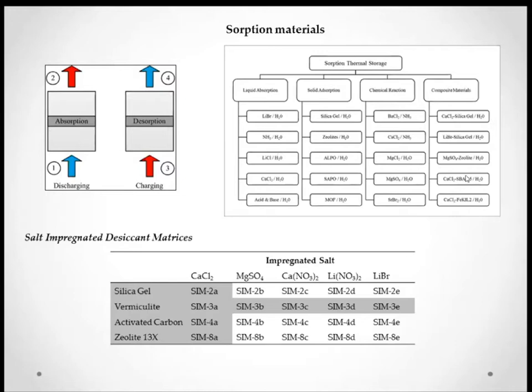Different materials are available in the literature, mainly composite materials using different host matrices to keep the salt inside, with the absorbent salt combined using different methods. Chemical reactions using water and salt-based composites can also be used. Conventional absorbents such as zeolite, silica gels, and liquid absorption processes are mainly used in absorption chiller applications. In our research, building on work pioneered by Professor Aristov, we developed several composites by impregnating salts in different host materials — we call them SIM materials, which stands for Salt In Matrix.